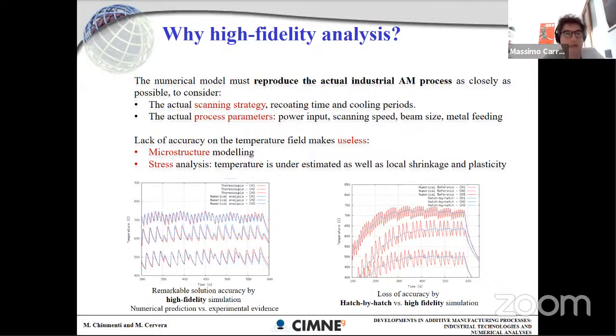So you say that you are looking at the component scale, but at the same time, you aim at high accuracy, especially in the stresses with this three-field formulation. Now, you do this simulation for the stresses with this octree adaptivity. So locally, you can be very accurate, but why do you need this accuracy at that local scale if at the end of the day, you will coarsen a lot in the part scale simulation? So the resolution of your stresses far away from the melt pool will not be so accurate.